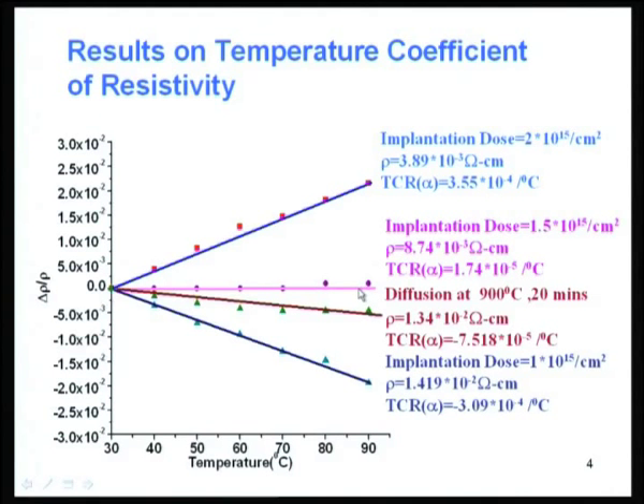But you can see, if I go to still higher doping, its behavior is almost like that of single crystal. It becomes positive temperature coefficient. That is not what you want. So, you have to adjust the doping. Okay. That doping level is about 5 times 10 to the power of 19 per centimeter cube. Okay. Now, let us see.